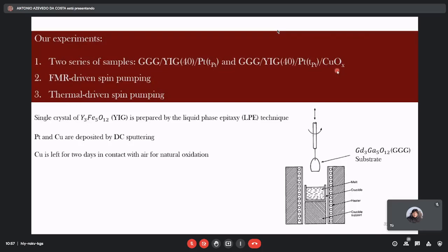If we deposit just copper oxide from a copper oxide sputtering target, the phenomenon doesn't happen. We do not understand why this happens, but it is the same phenomenon that happened in the two previous papers that I have shown.